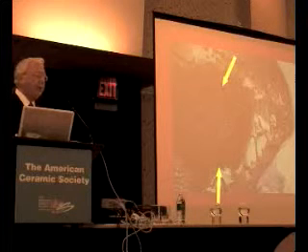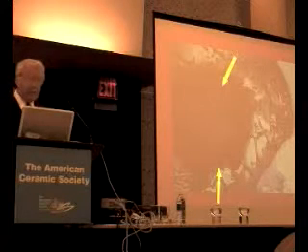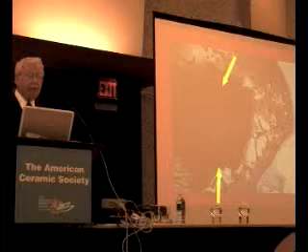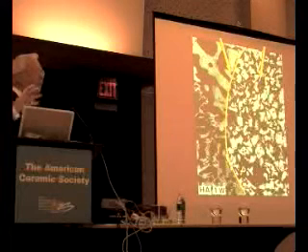We had a hypothesis that it was genetic stimulation by the ionic dissolution products that lead to the growth of new bone. The first quantified evidence of this came from an international collaboration between Professor Onishi's surgical team at the University of Osaka, Japan, and our group at Imperial College, where he developed a critical size defect model in rabbits. The defect was filled with powders, making it possible to quantify the kinetics of bone filling and regeneration over time.